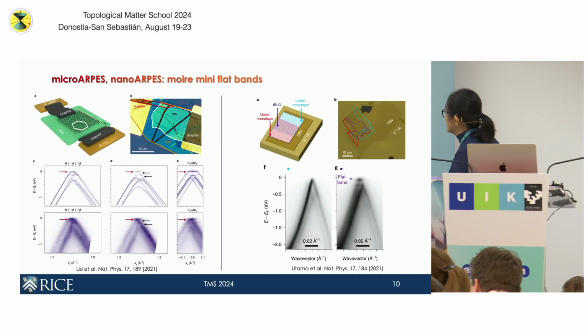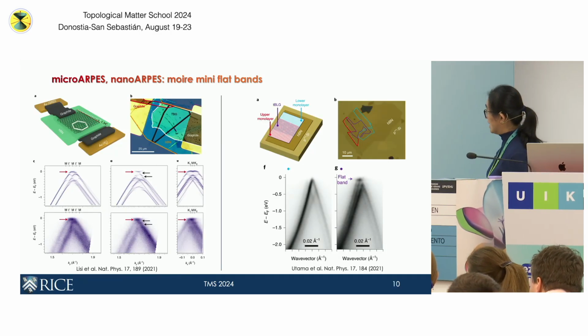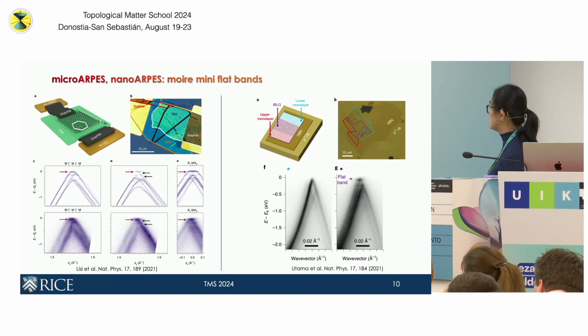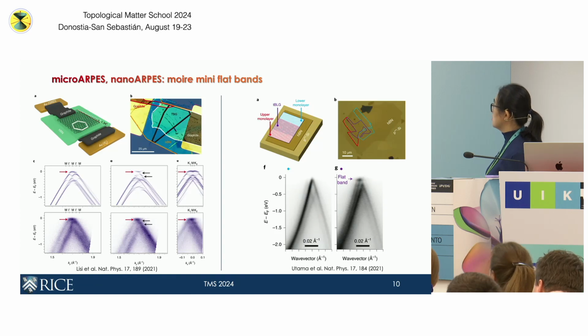And just for completeness, since a lot of people are interested in moiré, I think these two papers back to back were probably among the first to measure the moiré mini flat bands. I won't go into too much detail, but here in momentum space you can see the moiré flat band at the Fermi level for twisted bilayer graphene.